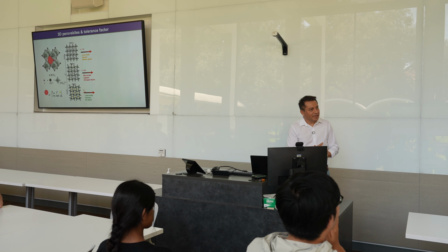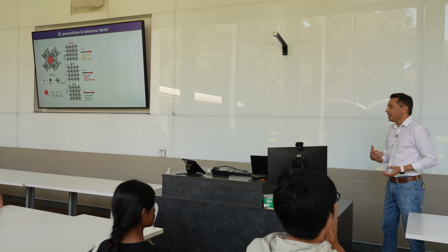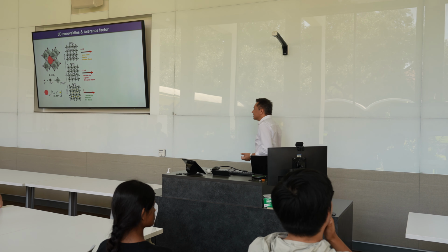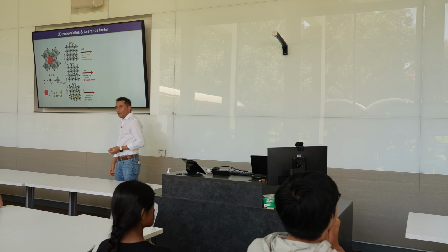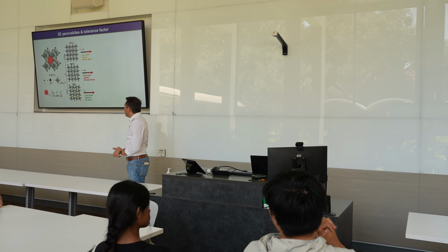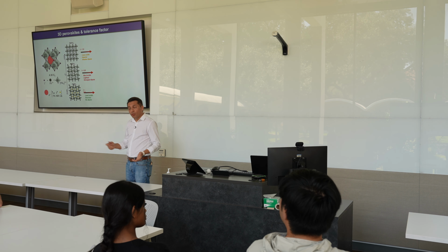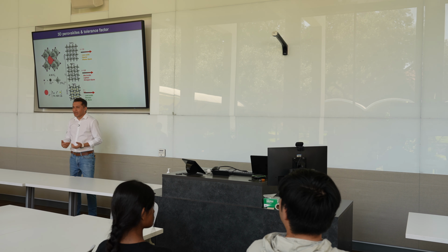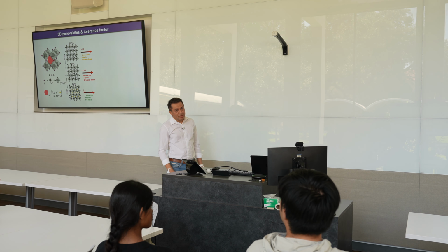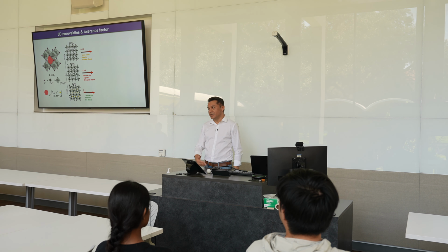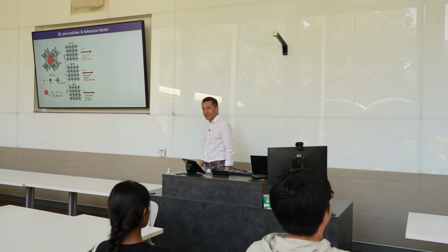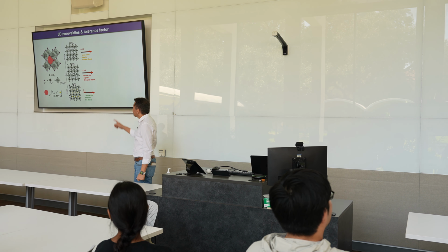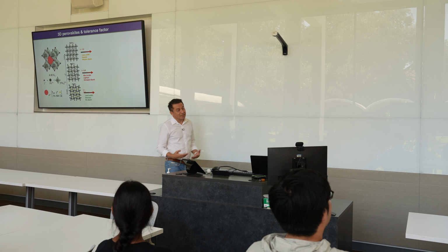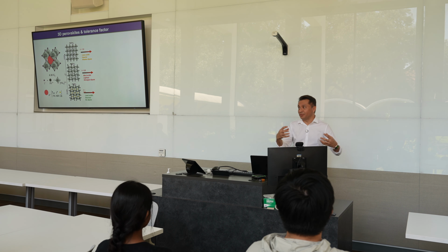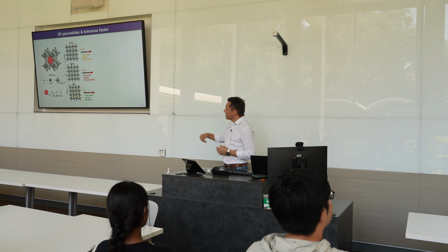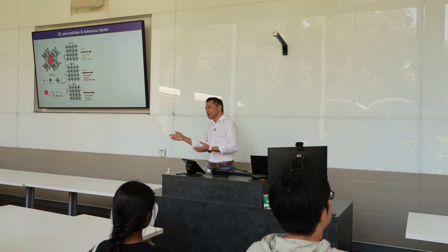Okay? So halide perovskites are like salt, common salt. They are ionic semiconductors, and they have this ABX3 structure, right, or AMX3 structure, where you have A, which is a monovalent cation, things like formamidinium, methylammonium, cesium. M is your metal, or B is your metal. It's a divalent metal, lead, tin, germanium, any divalent 2+ metal that you have. And then the X site is an anion, right, with a minus charge, and that's the electrostatics of it. That's what you put all of these things together. And typically this X in the halide perovskite is a halide. It's iodine, bromine, chlorine, right?